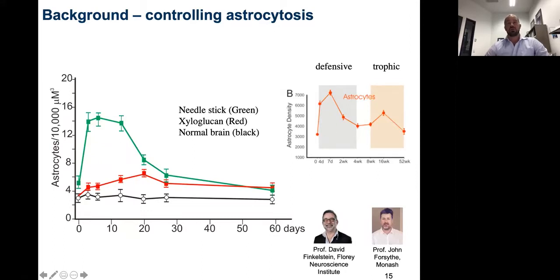Interestingly, when they switch from this inflammatory state, they increase a little bit at the 16-week time point as they switch back towards their cytotrophic behavior, where they physically and biochemically support neurons. That's their role: for a neuron to survive in your brain, it has to have a blood vessel and an astrocyte adjacent to it. But what we found is when we put in this hydrogel called xyloglucan, which is used as a thickening agent in Japan and is made from seaweed,